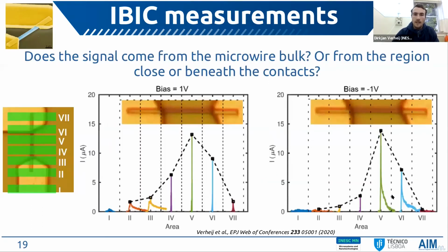Like I said, we are able to position the proton beam with micrometric precision, and this allows us to irradiate specific sections of the device. We did this because we wanted to study the influence of the contacts on the ionocurrent signal. We irradiated each of these sections individually and measured the ionocurrent, and we saw that for both negative and positive bias, the highest peak was obtained when irradiating the middle section of the sample. In fact, it looked like the contacts were in some way suppressing the ionocurrent signal.